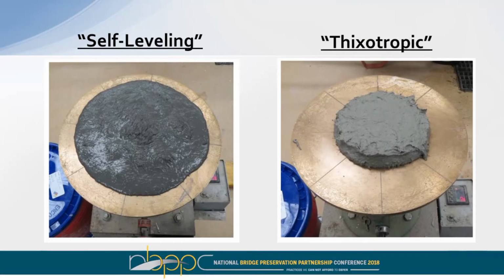On the other side, we have a thixotropic version. This is what we're going to use for overlays because bridges have slopes. And if we use a self-leveling product, it's going to go where gravity tells it to go. So we use a different admixture that gives it a little bit of a thickening behavior. But as you're imparting energy into it, the material looks like it's fluid. And as soon as you take away that energy, it stiffens up and maintains the form that it's in.